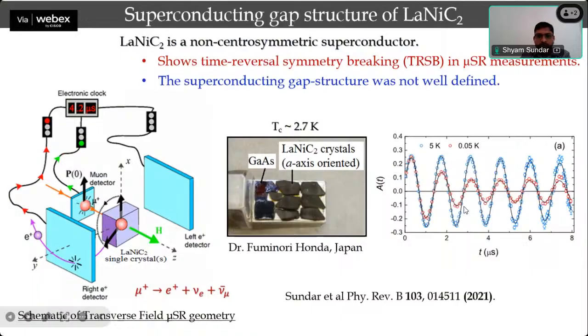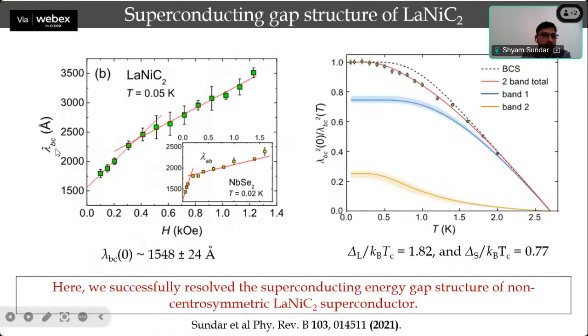Because of this relaxation, we can fit this data and get the penetration depth. And this is exactly what we did. We got this penetration depth as a function of field, which clearly shows two different slopes. And two different slopes are basically the characteristic of two different superconducting gaps. So we confirmed that there are two different superconducting gaps in lanthanum nickel carbide two, as was proposed theoretically.